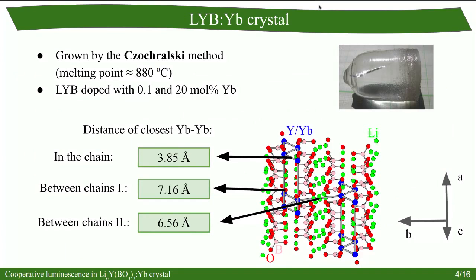We usually grow the lithium-yttrium borate crystals by the Czochralski method, and this crystal has a melting point of about 880 degrees centigrade. We measured the 0.1 and 20 mol percent ytterbium-doped lithium-yttrium borate crystals. It's very important that in the lattice the yttrium ions form a chain, and in the chain the neighboring yttrium ions have a distance of only 3.85 angstrom. And between the chains, the distance is much higher: 7.2 angstrom and 6.6 angstrom. This distance, 3.85 angstrom, makes possible the generation of ytterbium pair emissions in this host.